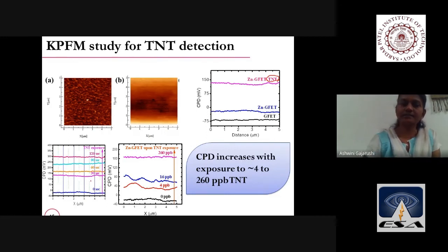So accordingly, we can find out for more exposure time also, and for increasing the exposure dose, like from 4 ppb to 260 ppb. If you see, there is a systematic increase in the contact potential difference. So this is how this atomic level interaction has been traced by means of these several systems.